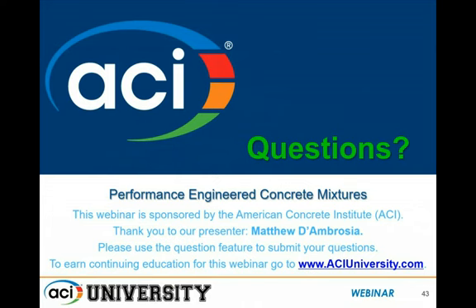Not necessarily. The compressive strength compatibility between the substrate and the repair material is not as important as the modulus compatibility. What you really need to match is the modulus of the repair and the modulus of the substrate, and that reduces the potential for concentrated stresses around cracks and joints and anywhere that could be a stress concentration. As I mentioned in the talk, we did focus on the modulus, and we tried to reduce the modulus essentially as we were working.